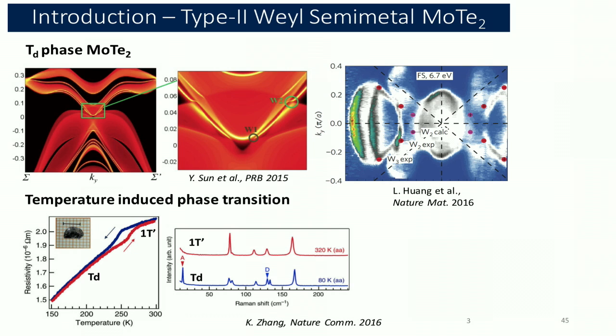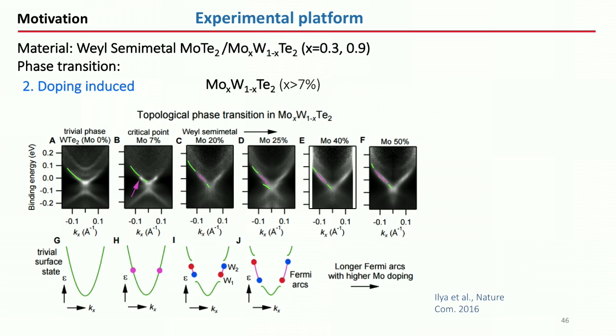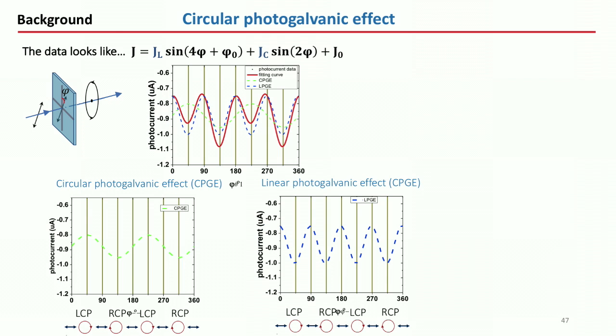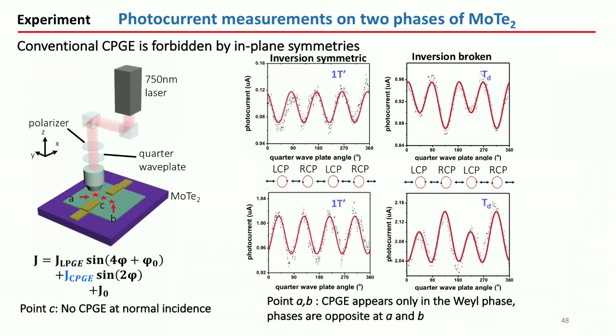So people have measured the dispersions using ARPES to confirm that it is a Weyl semimetal. All right, so the experiment is the following. If left and right circularly polarized light produce different photocurrent responses, that means it has the circular photogalvanic effect. So we started with this experiment on MoWTe2. At room temperature, as you can see, left and right circularly polarized light produce the same response. So it's not a Weyl semimetal. It has inversion symmetry, so no response.